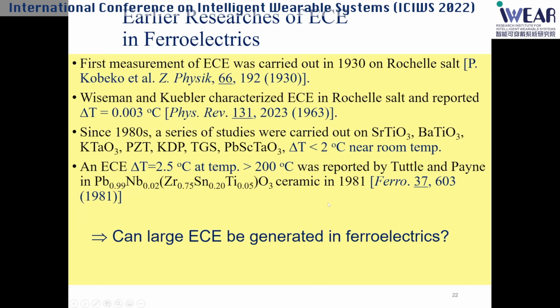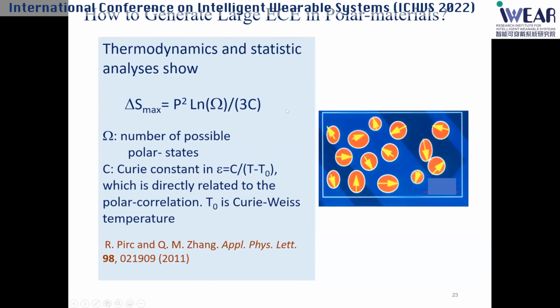The answer is not so hard, because we did some theoretical analysis with a group from Slovenia. Basically, the entropy change in electrocaloric material is proportional to the polarization squared — this is why we use ferroelectric material. But it's also related to the randomness of the material. This omega is the number of possible polar states, basically a measure of how random your polarization can be — it's a number of states.